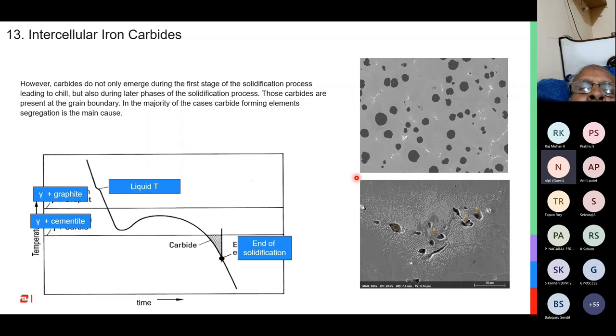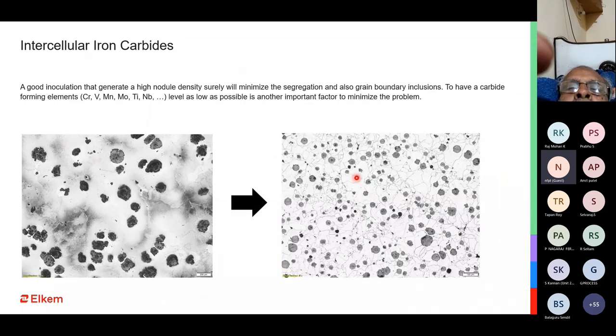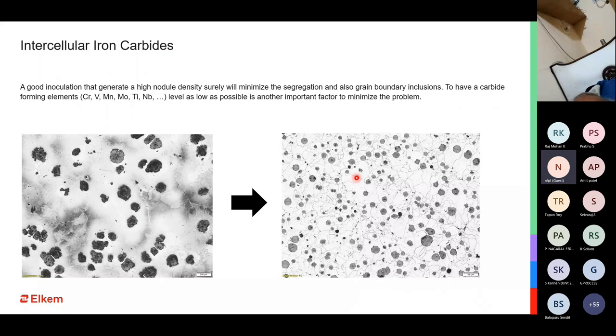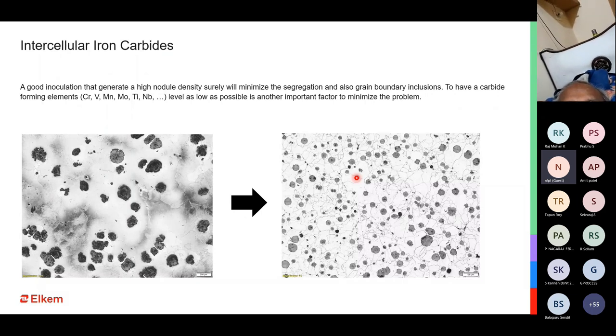The other reason for this kind of defect is when you have an inoculant which fades over time. When the inoculant fades during solidification, then at the end of solidification you do not have enough graphitization potential left in your metal. This metal will in turn be a home for carbide promotion, and thereby whatever carbon is present, instead of forming graphite, will combine with iron to form iron carbide, which is called inverse carbide, inverse chill, or intercellular iron carbides. A good inoculation that generates a high nodule density will minimize the segregation of these carbide promoting elements and also make sure that there is enough graphitization potential towards the end of solidification, and thereby you get an intercellular carbide free structure inside the casting.